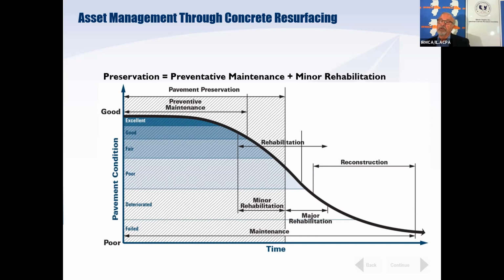For instance, if you see the preventive maintenance, we're talking about the need for full depth repairs. So you have a transverse crack that's opening up in the pavement and you want to repair that to keep moisture out, to keep incompressibles out. You could do a specific full depth repair relatively inexpensively. But what happens if every 5th slab exhibits that kind of behavior? We move down then into the rehabilitation cycle where we're doing substantially more than trying to maintain the pavement in a certain level of serviceability. We're actually down to the point where we are fixing it to keeping it in surface.